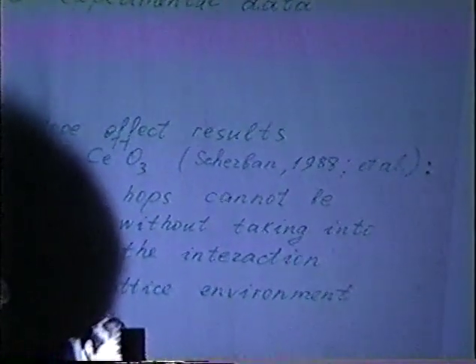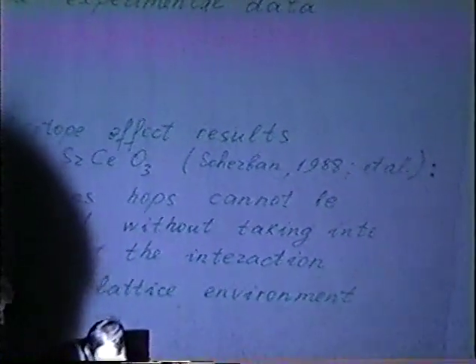Structure and structure changes. This problem is more complex in character than it seems. We conducted the analysis of X-ray structure data both before and after the experiment with the samples by a DRON diffractometer. Our X-ray study shows that the sample based on strontium cerium O3 has the orthorhombic structure.